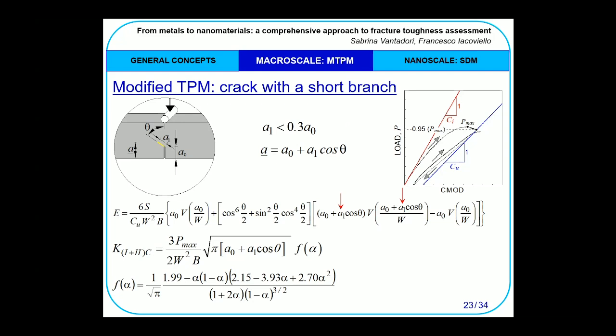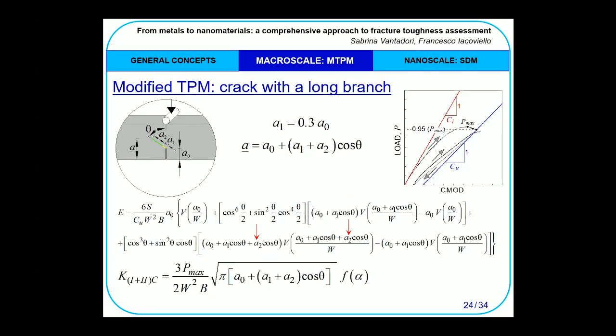Let's start with the case of the crack characterized by a short branch. By applying the Castigliano theorem, a different expression for the elastic modulus is derived, from which the length a1 can be calculated and consequently a underline. The fracture toughness is obtained by assuming a straight crack having a length equal to a underline. When the crack has a long branch, the crack is assumed to consist of two segments, named a1 and a2. In this case, a new expression of the elastic modulus is derived, from which the length a2 can be computed and consequently a underline. The fracture toughness is computed as previously discussed.